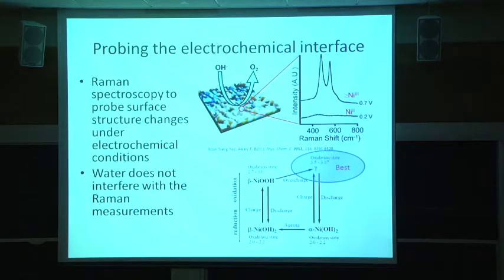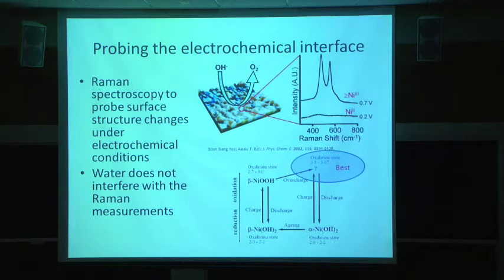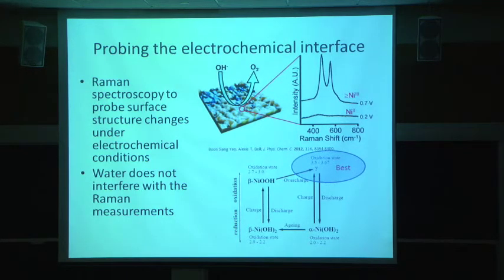Now we have to think about what's going on at the electrode surface. So what could be causing this promotion? We've been developing some Raman spectroscopy techniques in my lab. Alex Bell's group and others have used it on nickel oxide, where you can see at low potentials, where no oxygen evolution occurs, it's fairly featureless. As you increase the potential, you get oxidation from nickel 2 to nickel 3, and you get the formation of this new phase that is active under the evolution conditions.